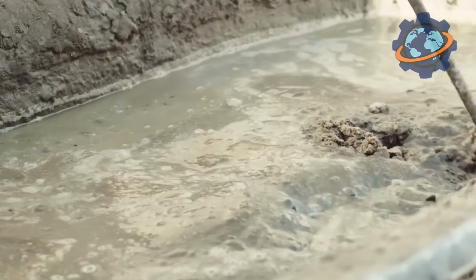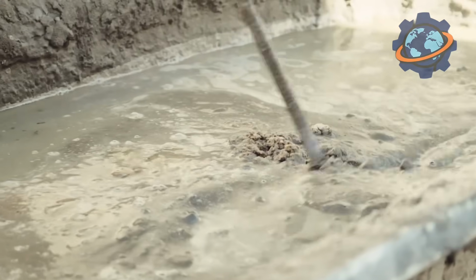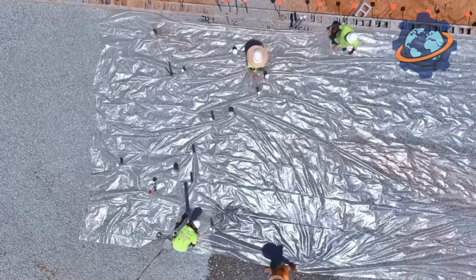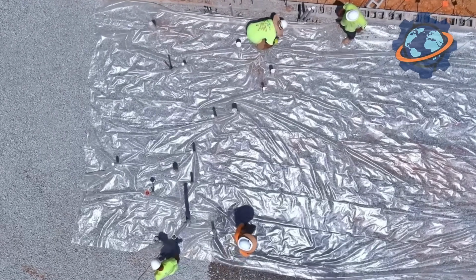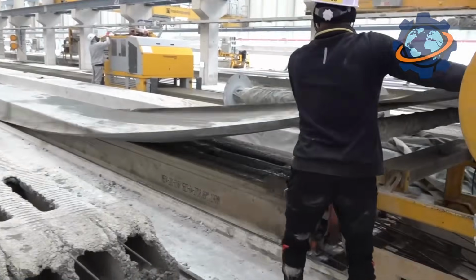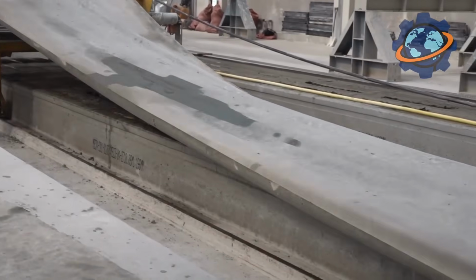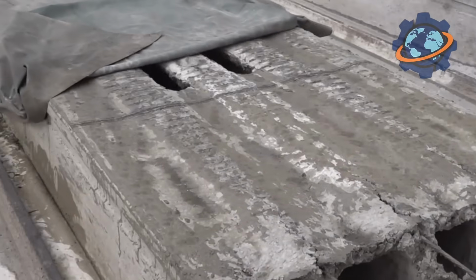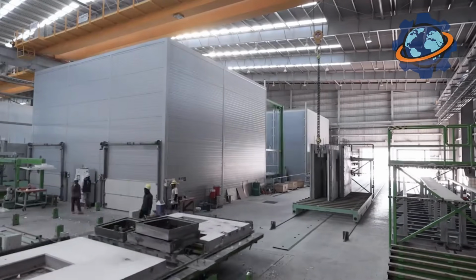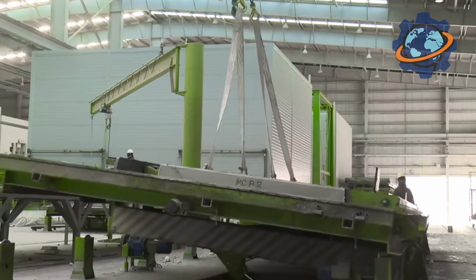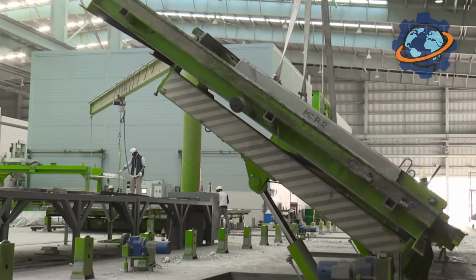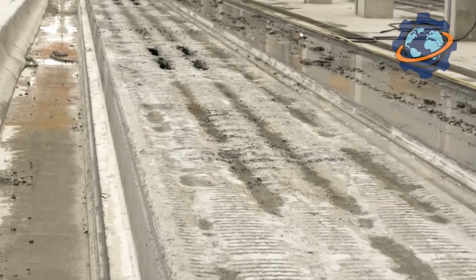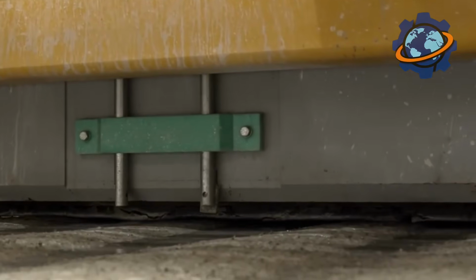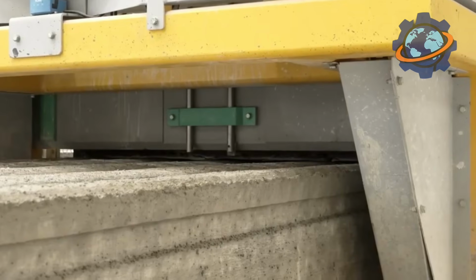Under normal conditions, concrete needs weeks to reach its full strength. But in this hot, humid atmosphere, it achieves the required strength of over 5,000 pounds per square inch in just 12 to 24 hours. When the concrete has set and become hard as rock, it's time for the release. Workers slowly let off the pressure on the hydraulic jacks. The tensioned steel strands, now permanently bonded to the concrete, try to shrink back to their original length. But the concrete won't let them. As a result, this massive compressive force is transferred to the concrete slab itself.